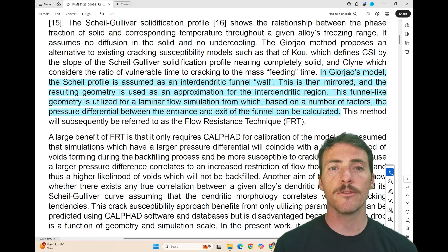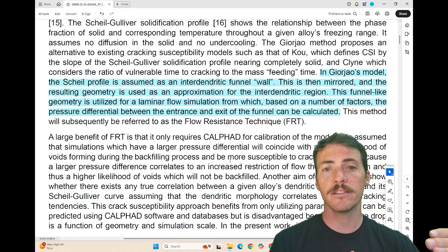This funnel-like geometry is used for laminar flow simulations, and from that you can actually back calculate the pressure differential between the entrance and the exit, which then they use to assess whether or not something is going to crack.